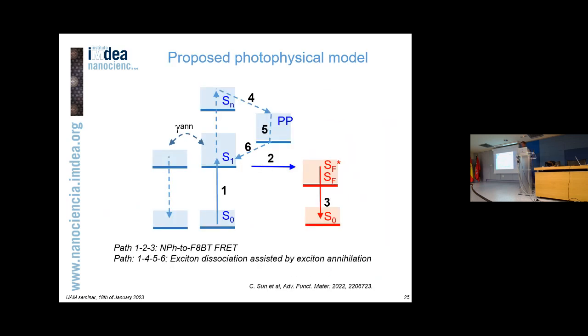But then we tried to understand a little bit why, and we performed global fit analysis. The idea is that we propose a series of coupled differential equations, and we try to fit the complete data set in order to find agreement with what we measure. It turned out that this photophysical model fit pretty well with the data.